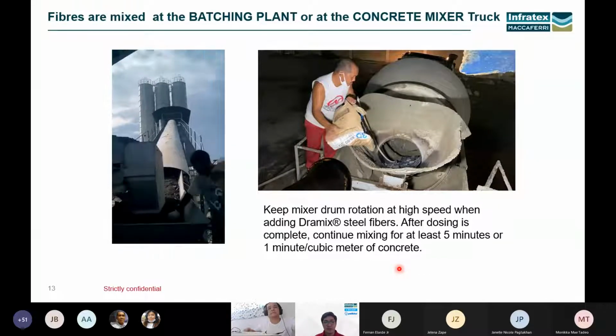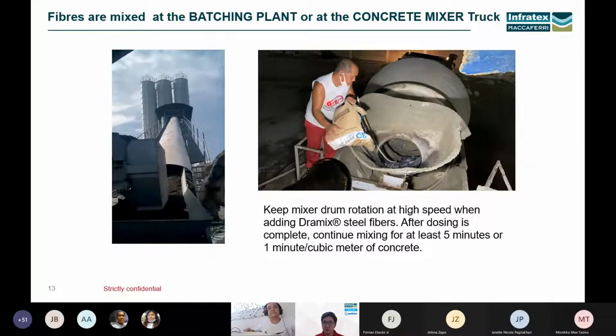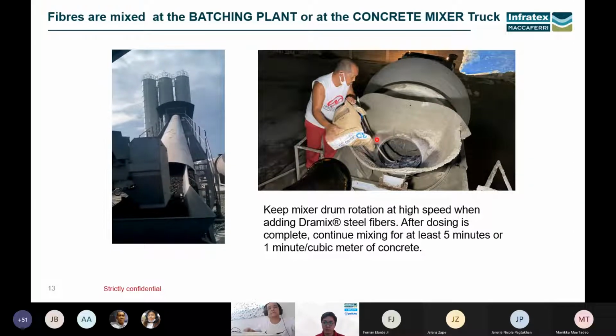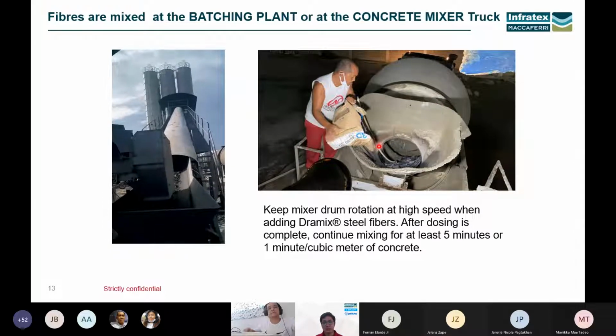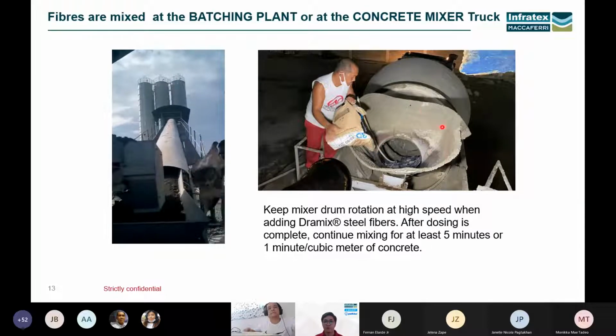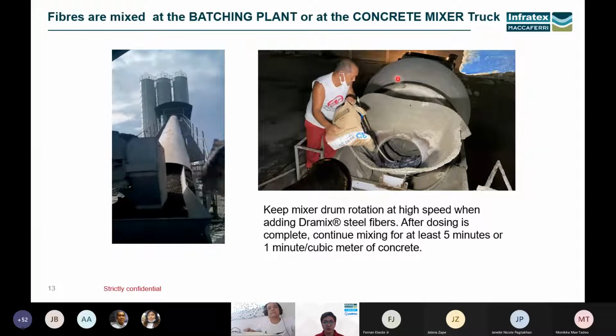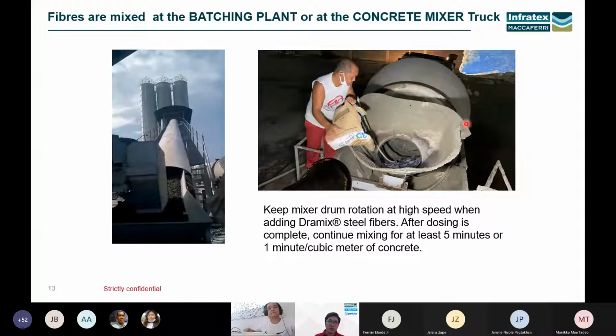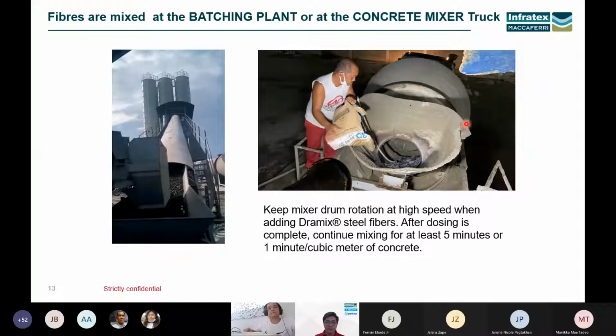However, if the situation requires us to do that at site, we can do that at the back of the mixing truck. Just remember that the drum speed must be at high speed, and after completely dosing the steel fibers, continue mixing for at least 5 minutes or 1 minute per cubic meter of concrete. So if you have 10 cubic meters of concrete in the mixing truck, continue mixing for 10 minutes.